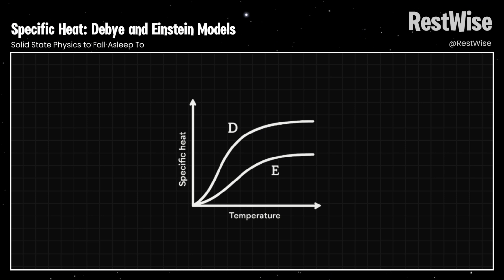At high temperatures, the Debye model also converges with the Dulong-Petit law, predicting a constant specific heat, just like classical physics would expect. This dual accuracy, matching both low and high temperature behavior, is what made the Debye model the standard for understanding specific heat in solids. The Debye temperature, a critical parameter in the model, is different for each material and indicates the point where quantum effects begin to significantly affect specific heat. For example, lead has a relatively low Debye temperature, meaning quantum effects fade at lower temperatures, while diamond has a very high Debye temperature, so quantum effects persist even at room temperature.